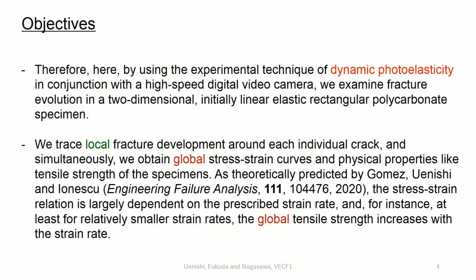As theoretically predicted by Gomez, Uenishi, and Ionescu in the journal Engineering Failure Analysis in 2020, the stress-strain relation is largely dependent on the prescribed strain rate, and, for instance, at least for relatively smaller strain rates, the global tensile strength increases with the strain rate.